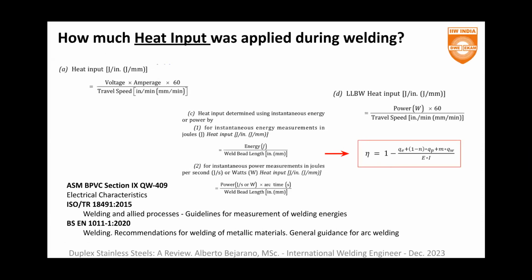The cooling rate depends on the thermal properties of the material, and on the quantity of heat that the base metal receives. This is quite important, and we have to talk about some details here. Normally, the heat input is calculated by the use of the arc power, which means voltage multiplied by amperage, divided by the travel speed, which is a classical, traditional point of view, but